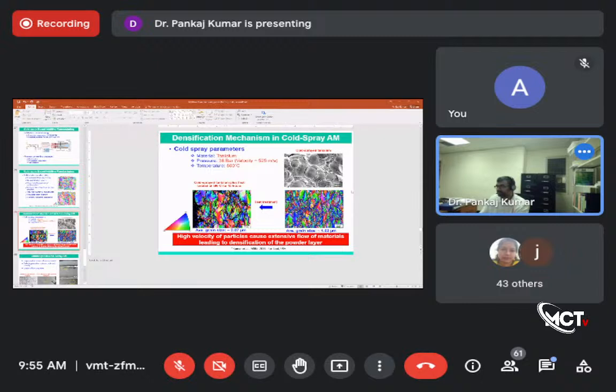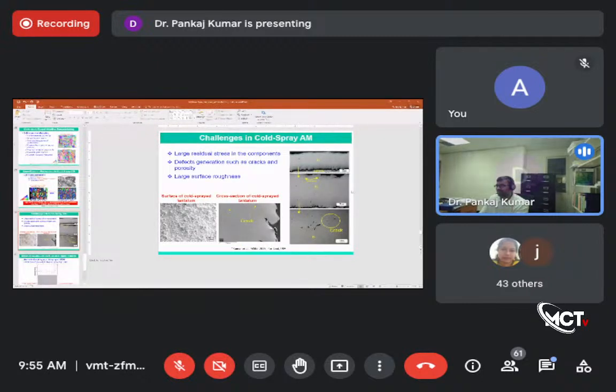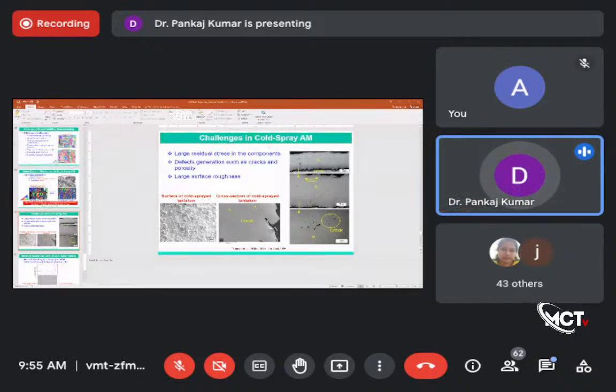Okay. So what are the challenges with the cold spray processes? Right. You have, of course, the defects, right? The porosity you see, right? You have the micropores, and this is an example of titanium. Okay. So titanium is actually deposited on this layer, magnesium alloys. So you can have the micropores and you can have the cracks. So cracking is always a problem because you are spending so much strain energy, right? And because of that strain energy, you see the crack.